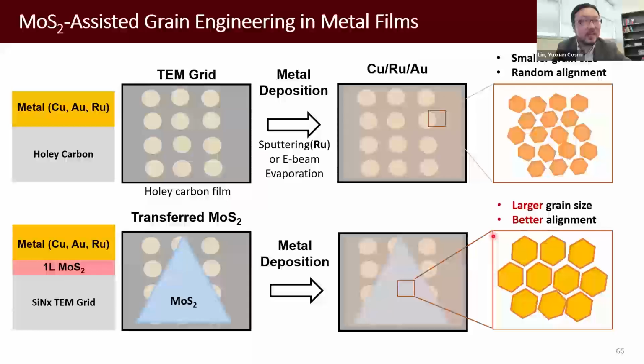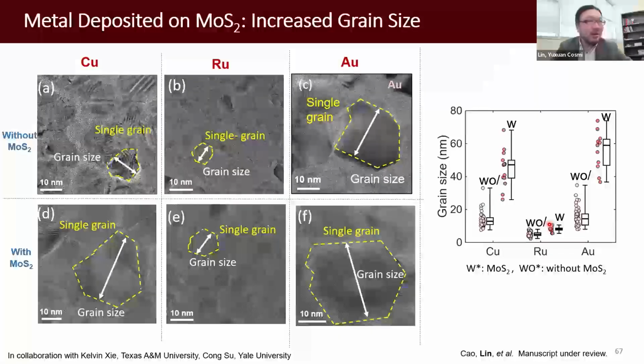So based on this understanding, we designed this experiment. Based on the TEM grid system, we deposit a different metal on a holey carbon film, or we transfer MoS2 on this silicon nitride TEM grid and then deposit the metal. And then we use TEM to characterize the microstructure of the deposited thin film. So these are all 10 nanometer films: copper, ruthenium, and gold.